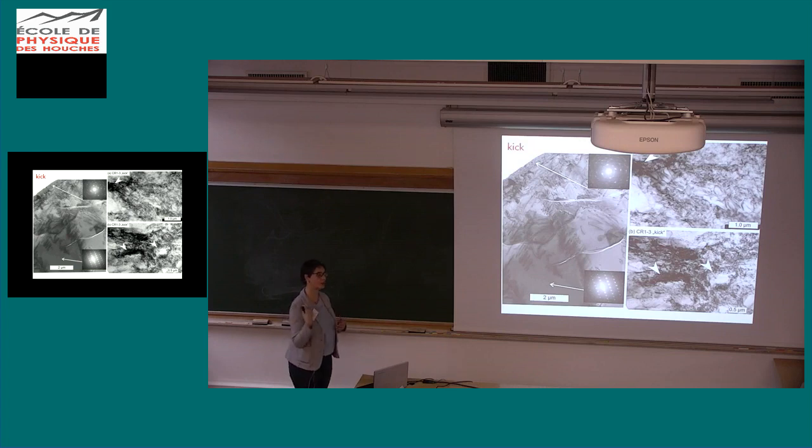So we have put a lot of strain energy in our system, which is stored within these microstructures. And we do see, highlighted by these arrows, within this forest areas that have a low dislocation density. So we call that a cellular structure, which means that we have cells of low dislocation density covered by a high dislocation density crystal volume.